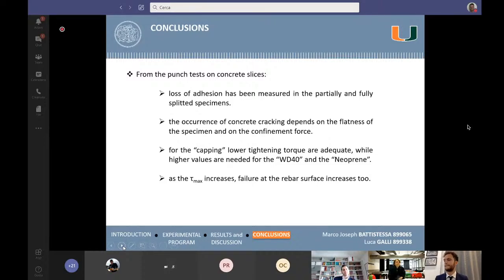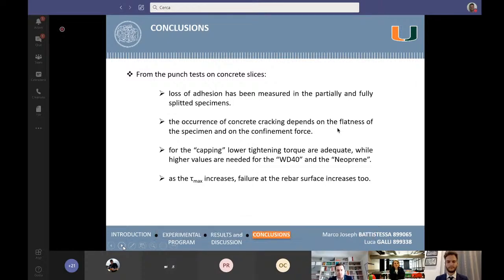Okay, from the test carried out on this thesis work, we can draw the following conclusion. So we have combined different combinations of confinement forces and different specimen support configurations to define a proper setup for the punch test and to avoid the concrete splitting of the sample. A loss of adhesion has been measured in the partially and fully split specimens, and we have also observed that the occurrence of the concrete cracking depends on the flatness of the specimen and also on the confinement force.